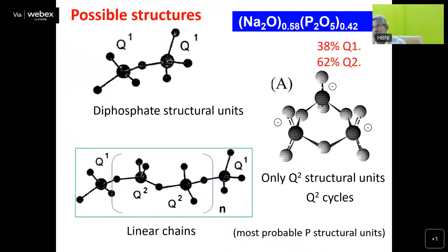So this is not a good situation, because the moment you put this glass in water, normally sodium ions undergo exchange, or sodium can be replaced by hydrogen or H+. So this type of exchange takes place. In addition to that, this also deteriorates the glass property. So this type of long chain is always good. If you can get it, well and good.